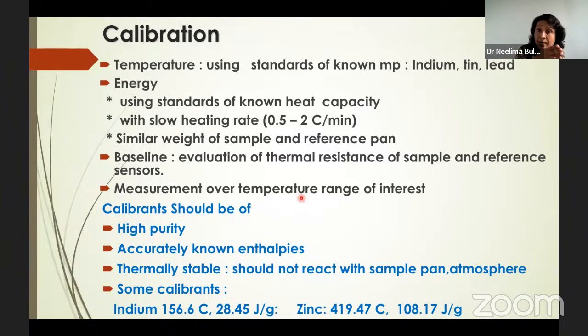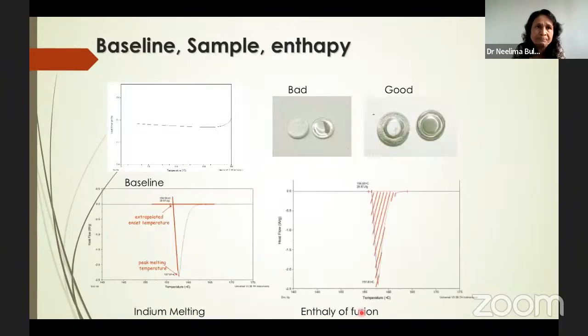See that your sample and reference pans have similar weight. Your baseline is straight, and then measure over the temperature of interest its melting and heat capacity change of that standard material. So the calibrant, we call it standard material, should be of high purity with accurately known enthalpies. It should not react with the sample pan or atmosphere. For example, indium has its melting point at 156.6, and its heat capacity is also known. So there are different metal standards for different temperatures.